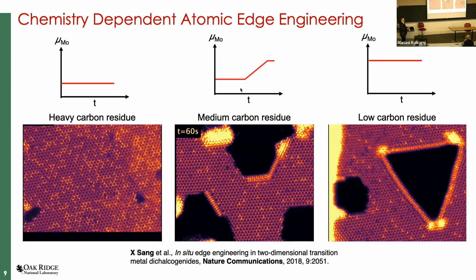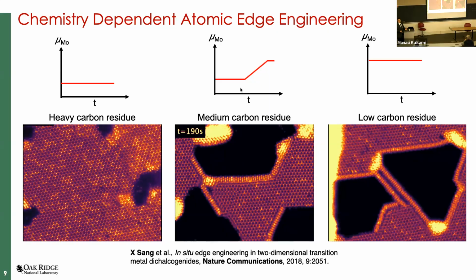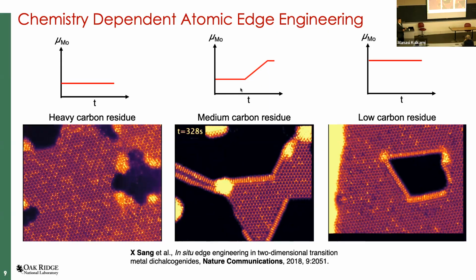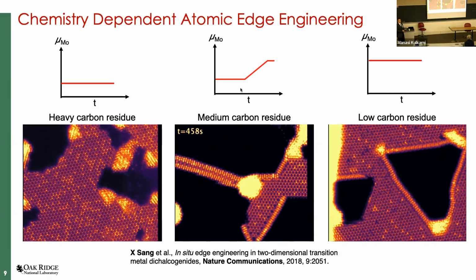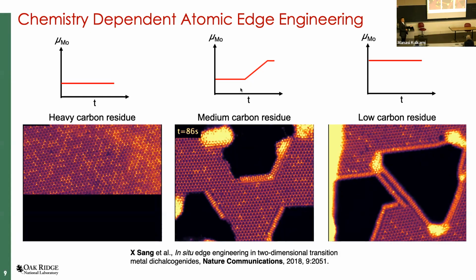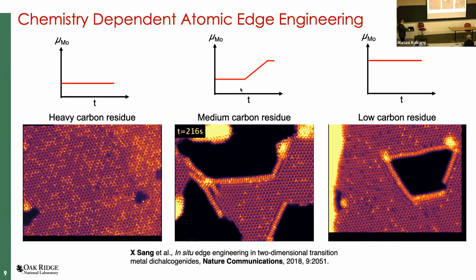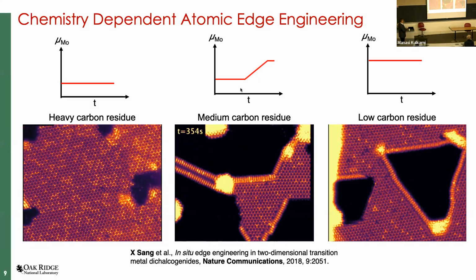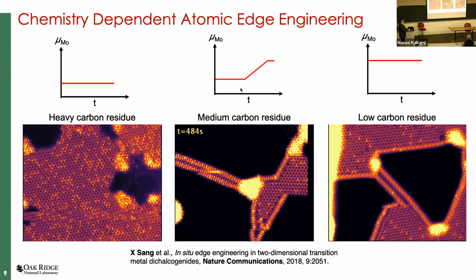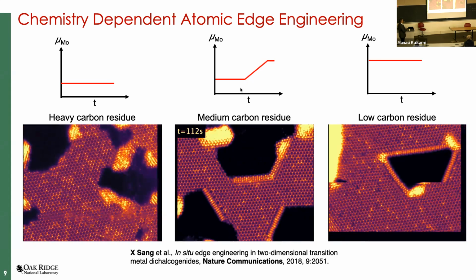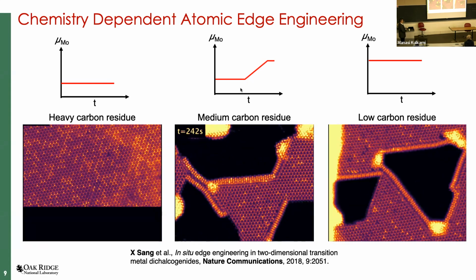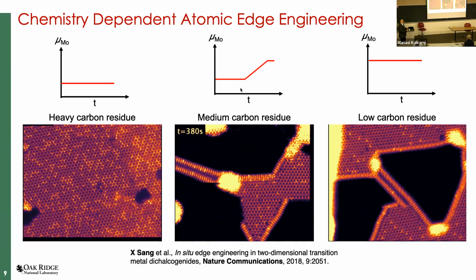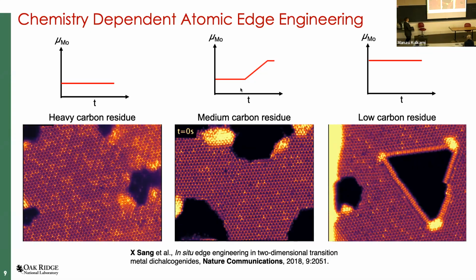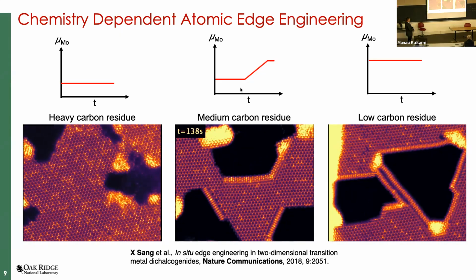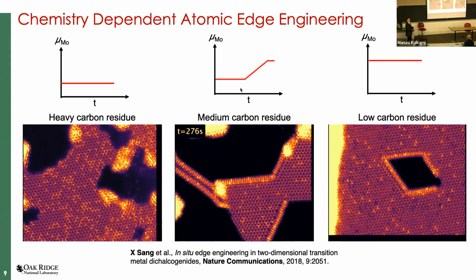If an area is on a 2D material because you're transferring it from a polymer like PMMA, you're going to have this gooey residue on the surface. Sometimes it's unavoidable. That interacts during the whole transformation process. So what I try to do is look at the chemical potential, and I'll get to that a little bit more in time for folks that are studying thermodynamics as a function of time. So if we have a lot of residue that's built up, we start to have a propensity to form more of these ball-like moly carbides. So if we look at regions where we're transforming with medium and even low residue, we have different structures that form. So I'll explain that a little bit more in a second.